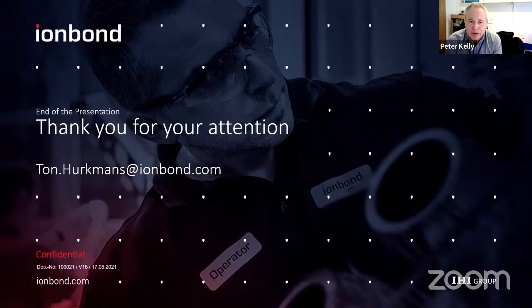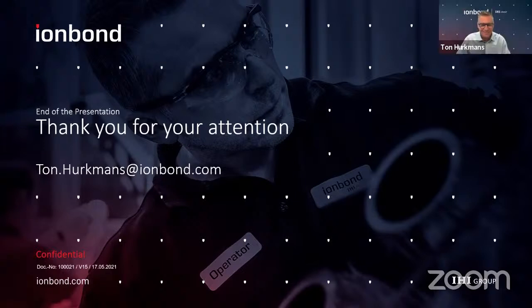Another question, have you any experiences of coating cemented carbide tools for milling compacted pearlitic cast irons? What is the best coating nanolayer structure? Yes, we coat cemented carbide substrates all day long, and we have a wide portfolio for cast iron. I must admit, we have so-called segment managers that are the specialists more than I am on the details. But typically, my first guess would be chromium aluminum nitride type of coatings. Crosscut is our trade name in that direction, being used as a kind of generic coating, including cast iron with the nodules and abrasive type of substrate material. But I would recommend to contact me separately, and I can give you a 100% full answer through, let's say, our specialist. So I apologize to hold back, but we definitely have solutions, but I cannot say for 100% sure that's just the one and the only one.